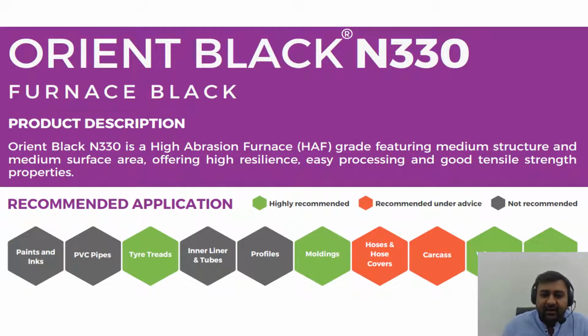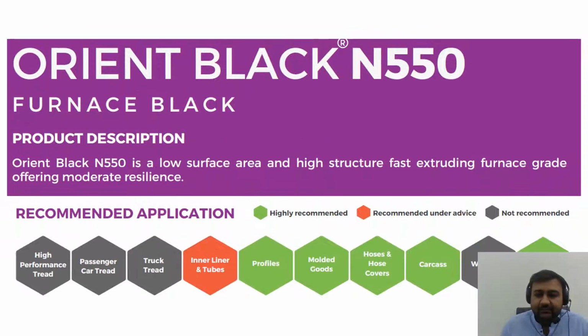This is one grade of carbon black, N330, which is a furnace black, and it imparts high abrasion property to the rubber, which is high resilience and imparts good tensile strength properties to the rubber. So these are the recommended applications where this type of filler can be used. We used another type of filler, which is N550. It is a fast extrusion furnace black which provides moderate resilience, and it imparts very good mechanical properties.